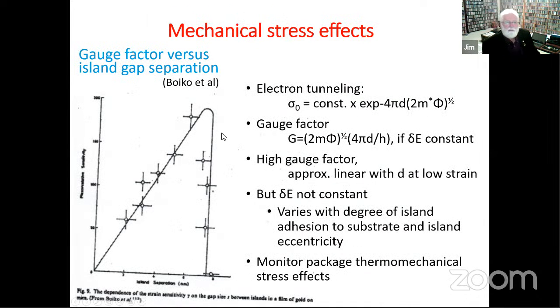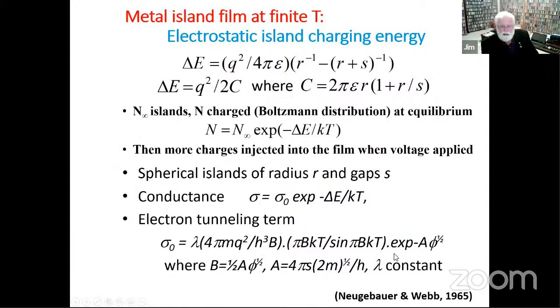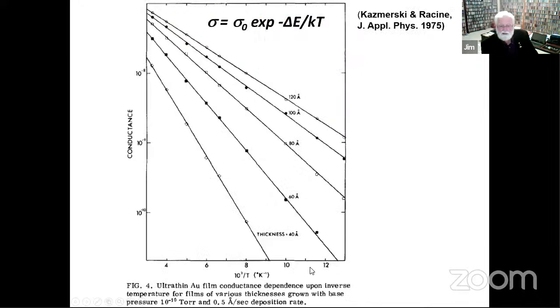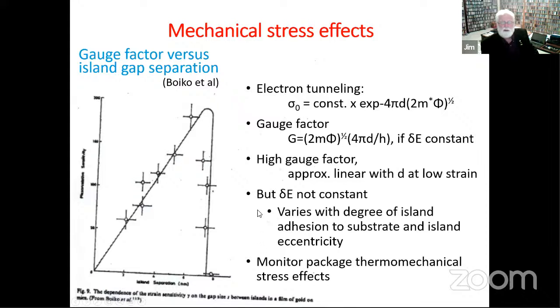So why are we interested? Well, if you have the resistance in an electron tunneling effect between islands, if you pull those islands apart, remember, this exponential term here includes the separation of the islands. So if you pull those islands apart, s increases, and then the resistance goes up. This is basically a strain gauge. And due to the electrical tunneling, this is s on the slides before, we can have a gauge factor, provided the activation energy is constant, of this form.